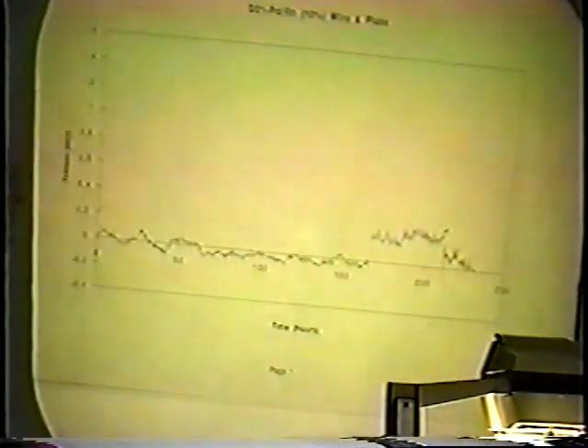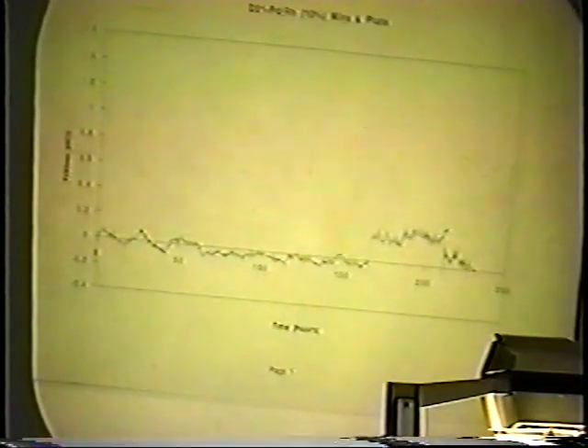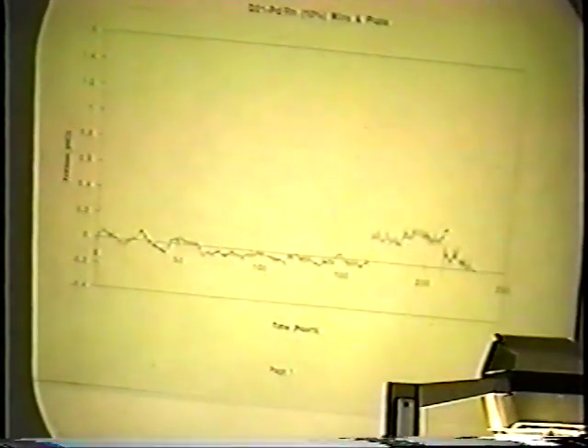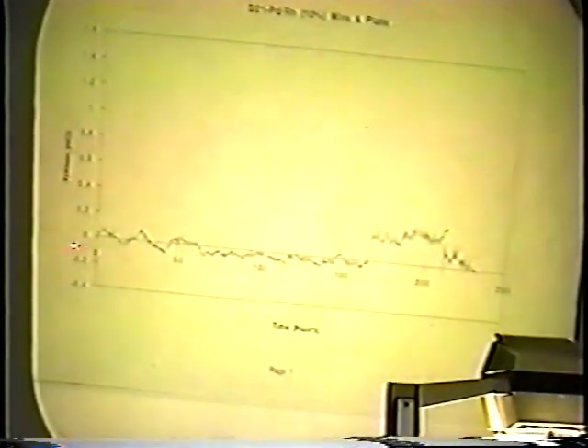Now here's sort of the break that we got. This is the palladium rhodium, and I think there's a paper published in Fusion Technology that I saw. Well, we had this a while ago, but this is again a confirmatory sort of thing. So here it's sort of flat. That's 150 hours. Didn't really drift down. That's good, but it's not too spectacular. And then it pops up at the end. It pops up a little bit more than the other ones.